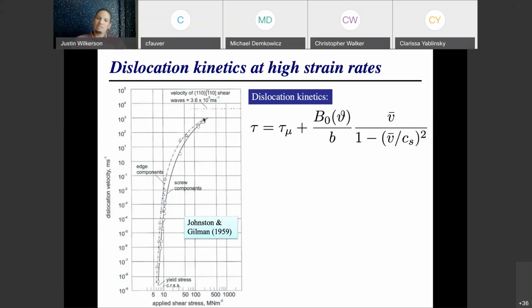For both dislocations and cracks, there are some special situations where you can have supersonic cracks or supersonic dislocation motion. For supersonic cracks, there's some really nice work that was done by Ares Rosakis, as well as Huajian Gao and Marcus Buehler, where they showed how you can have supersonic cracks, and also the implications of supersonic cracks on earthquakes, how you can have a more devastating earthquake if the fault tends to propagate supersonically. And here by supersonic, we mean for cracks, speeds that are higher than the Rayleigh wave speed, or for dislocations, dislocation motion that is higher than the shear wave speed of the material. Both of those have been observed, especially in molecular dynamics calculations.